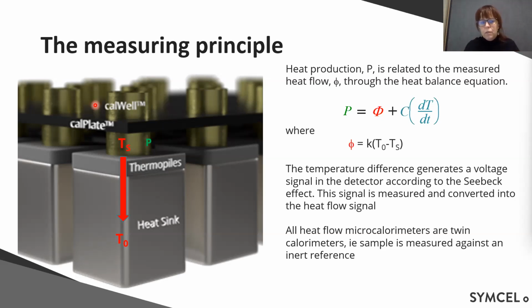So what we do with the physical contact onto the detector is that we are channeling all heat that is produced through the detector and out in the heat sink. So if you have a sample that is producing heat, we call the heat P, heat production in the sample. And that's related to the heat flow we are measuring through this heat balance equation. So we have the heat production. It's related to the measured heat flow and some kind of heat capacity term. The heat capacity term is because everything will store some heat due to a temperature difference, but for slow reactions, or steady state reactions, this will be near zero and will not be part of the equation.